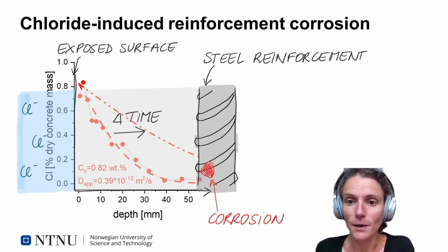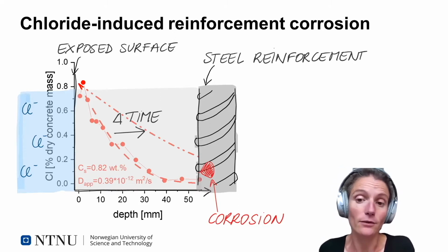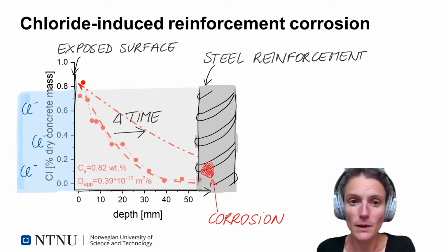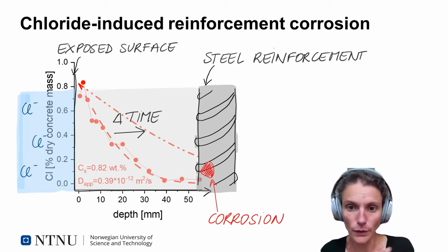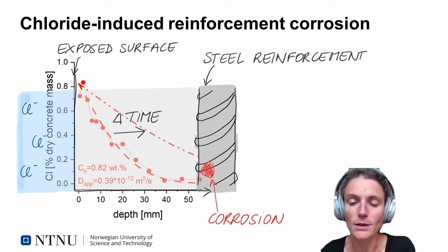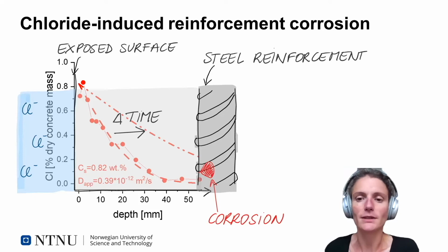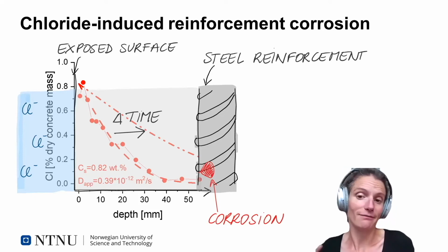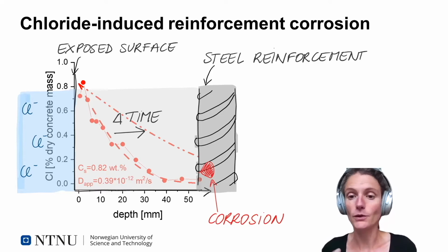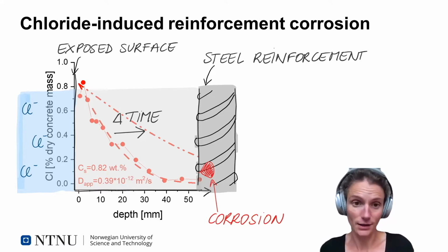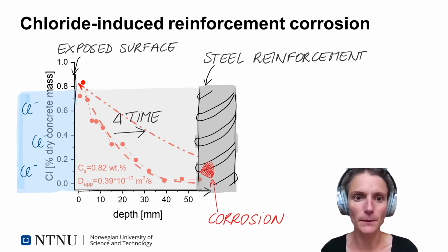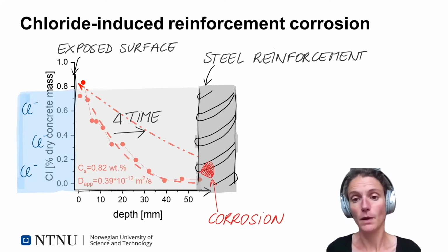So, for example, the model described in the fib model code or in the ISO standard relies on an empirical model. So what we do is we fit the error function solution from Fick's second law through the chloride profile, and you obtain some fitting parameters such as a surface concentration and an apparent diffusion coefficient. The challenge is that these empirical models rely on long-term field exposed data, such as these chloride profiles, in order to be reliable.